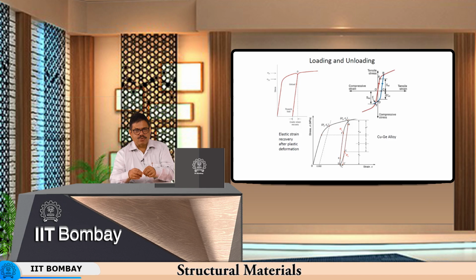For example, if you subject it to tensile compressive stresses successively over a number of cycles, you keep on reducing the yield point of the material due to this Bauschinger effect, and then it will fail. So, if the stress level had been within the elastic limit, it would have continued for a long period of time, and it would not have broken. But since you have gone to the plastic range, the yield point gets affected, the yield point comes down, and at some point it will reach 0 and finally it will break. So, this is one thing that needs to be kept in mind. The Bauschinger effect is a result of reversing stresses, and so in a rotating bending scenario, if the outer fiber were to cross the yield point, the inner fiber were to cross the yield point, then within a few cycles the shaft will start developing cracks from the surface inwards.